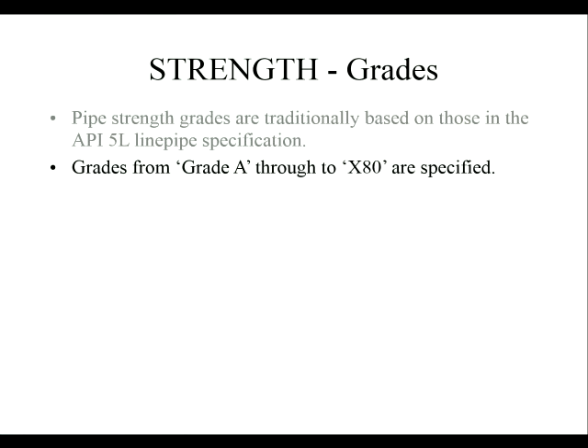So up to about X80 are specified and widely used. You can get X100 and X120 and even X200, but they are experimental grades. They're very rarely used. I think X100's been used on one set of pipelines in Canada, and the Japanese have produced it, been trying to sell it for some time, but the industry moves very slowly. So in this country, X70 used to be the limit, and X80 was unusual. Now X80 is quite widely used, but that's about where we've got. So X100 is not there yet. No.